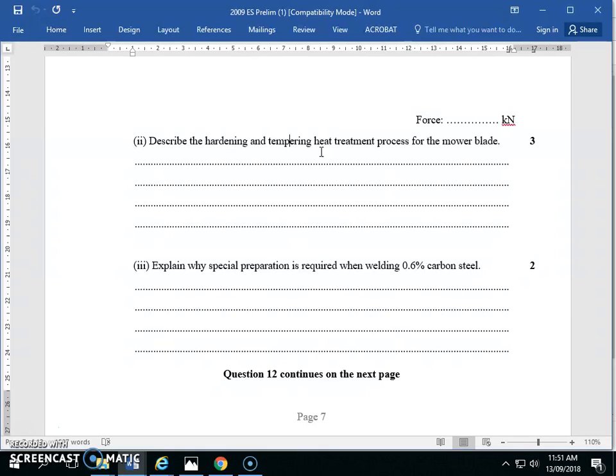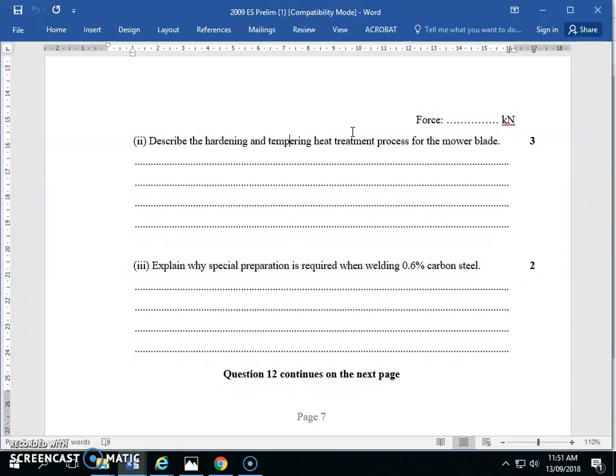The problem is that Martensite is no good. Martensite is very, very strong, very, very hard, which is good for a sword. We want it very hard and strong. But as soon as it hits another sword or shield, it shatters. So what do we do? We temper it. We heat it up. What temperature and for how long depends on the carbon content. We never heat it past into the austenite range - it's always less than red hot. We heat it for a bit and release some of that stress. The microstructure still looks like Martensite - it's just tempered Martensite, still acicular.